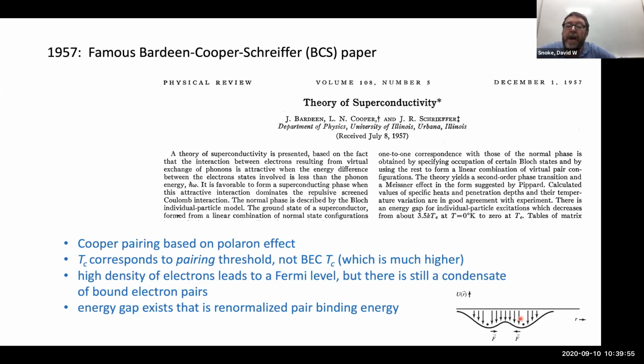And so if the condensate TC is much higher than the pairing TC, then as soon as you get to pairs, you're also automatically a BEC. But it doesn't have to be that way. Some people have proposed with some superconductors that you first have pairing at high temperature, and then you have to drop the temperature below a lower TC before you actually get BEC. And that's still a controversy. They call that a preformed pairs threshold. And that's still somewhat a topic of debate for high TCs.